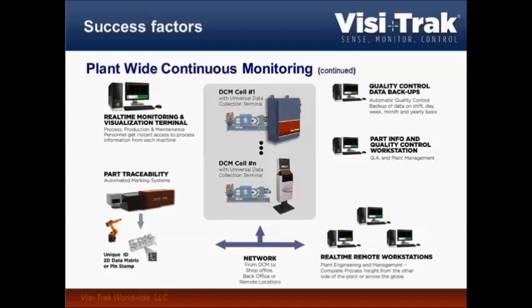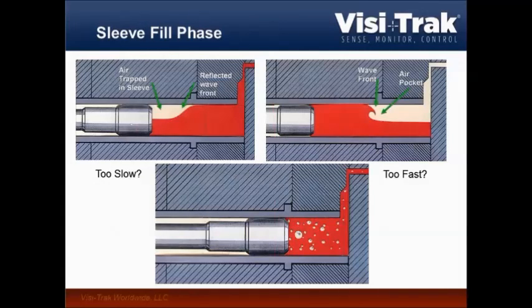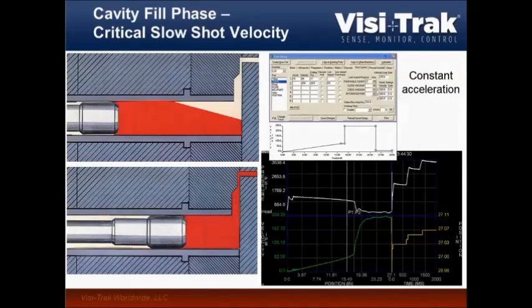So you want to make sure that all your process parameters were exactly where they're supposed to be. We talked about that slow shot, the fill phase, and I'm sure you are familiar with this. What you want to have is not too slow, like on the left side, where the metal front actually then comes back. Not too fast, where we build a wave and then fold in the oxide layer again and end up, in both cases, with a lot of bubbles in the melt that will end up as porosity in the part. What we want is a completely controllable linear ramp up of the slow shot, and therefore a nice metal front running in front of the plunger.